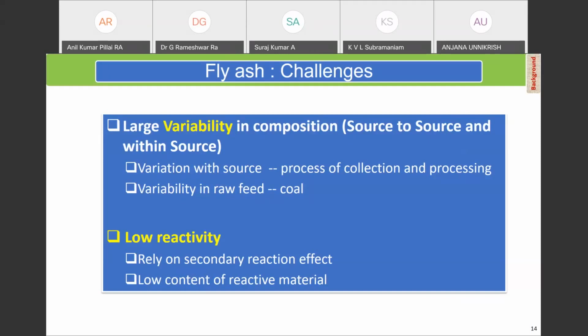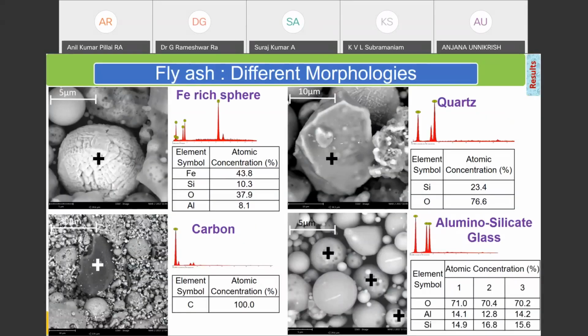It is a low reactive material compared to fly ash produced in other countries. Fly ash produced in India is not as reactive. So we started studying fly ash just to understand it, to see how we could maximize the utilization of fly ash. And if you actually look at fly ash under the microscope, you see that it's a very complex material. It contains these iron-rich particles. It has a lot of quartz in it. And quartz is basically silicon and oxygen. Basically, it's silicon oxide. And a lot of the silica that is present in the fly ash is present in the form of quartz. And the problem with quartz is it is one of the most unreactive materials known to man. It is sand, basically. And sand, as we know, is not reactive.